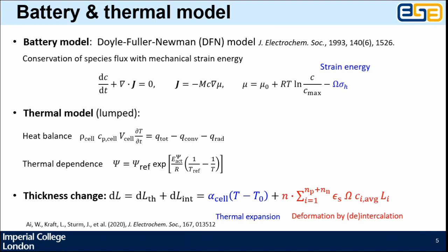For battery model, we used the Doyle-Fuller-Newman model, and we made some modifications by introducing the mechanical strain energy into the chemical potential energy, and then modifies the conservation of species flux.